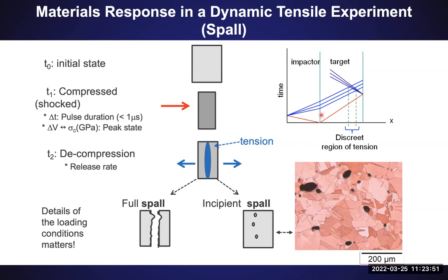So your impactor hits your target. That gives rise to a shock wave in your target and a shock wave in your impactor. These shock waves travel to the free surface of both the target and the impactor. And then you get these things, the blue lines here, called release waves, that basically are trying to bring your material down to zero stress. When these release waves intersect, it basically creates a region of tension. And depending on how hard this target was impacted, two things can happen. One, the material can fall apart into two pieces. We term that full spall.